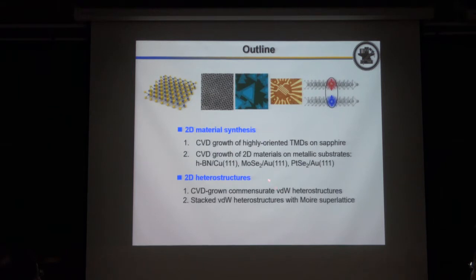So we take the advantage of CVD growth, so we can grow so-called commensurate vertical van der Waals heterostructure. And this is not possible to achieve by mechanical stacking, because with mechanical stacking you cannot control the atomic registry down to atomic scale. So you may form some Moiré superlattice.